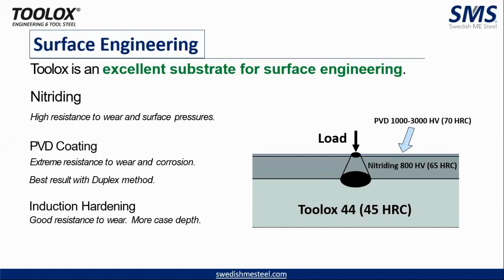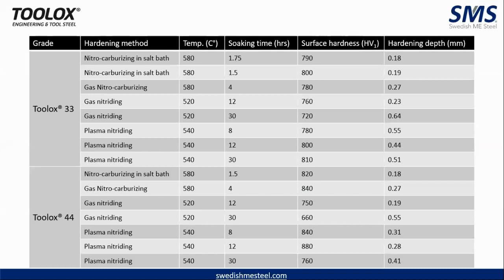You name nitriding, you can do it. PVD coating, you can do. Induction hardening, you can do. Even laser hardening is possible with Toolox 44. So this graph gives you an idea about what are the different values that you can achieve in Toolox 44 and 33: the different varieties of nitriding and the temperature involved, the different soaking time that each process requires, as well as what hardness it can achieve and what hardening depth it can go to. So for both Toolox 33 and 44, you'll be able to do nitriding, no problem.